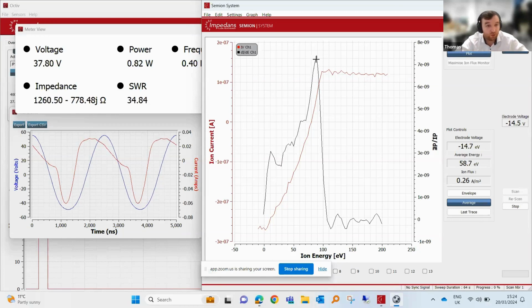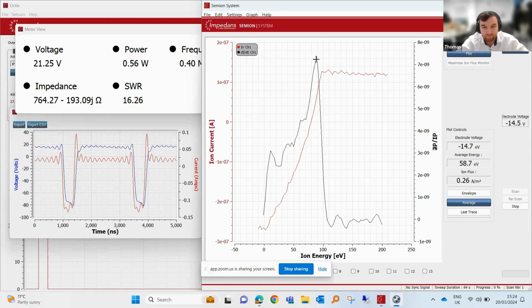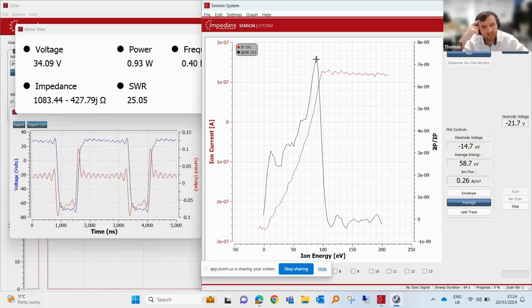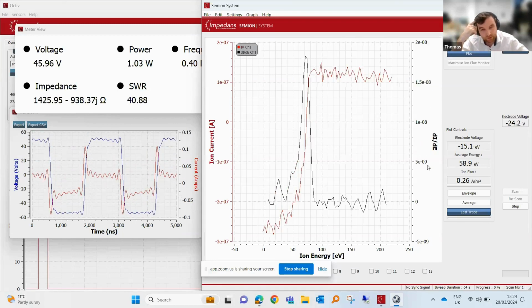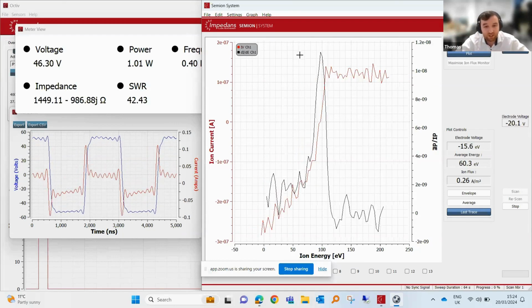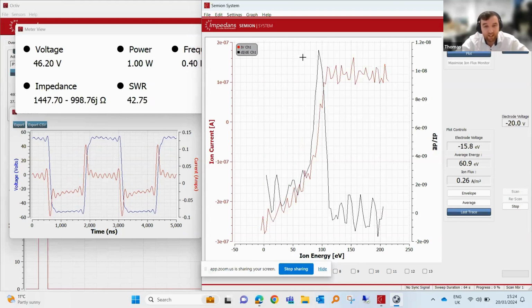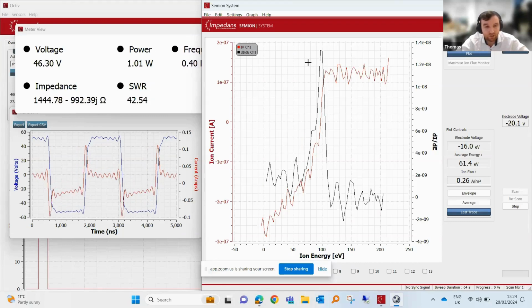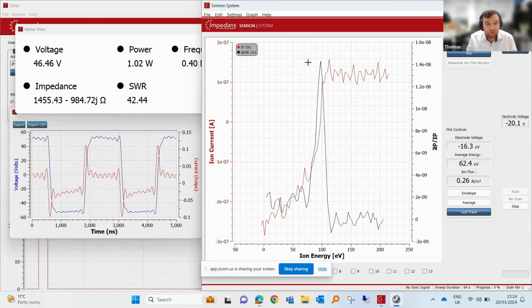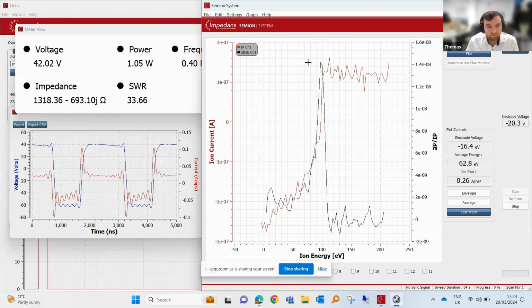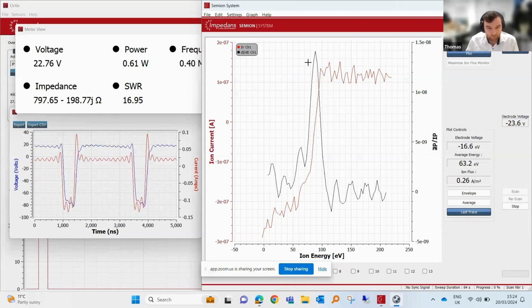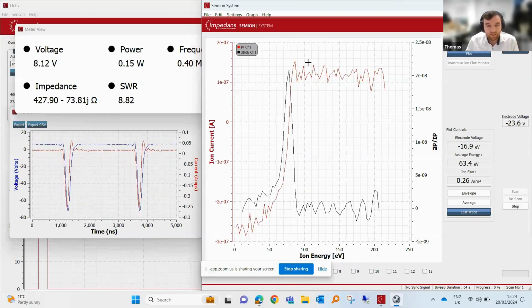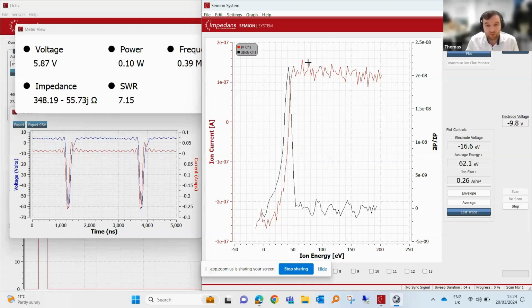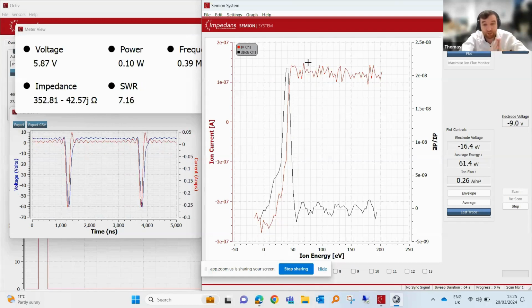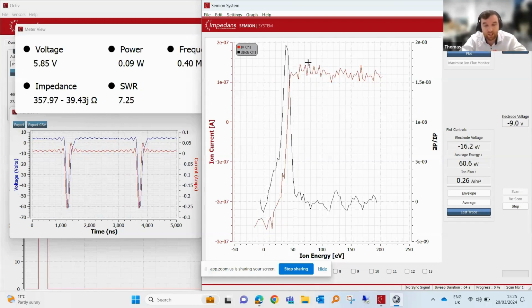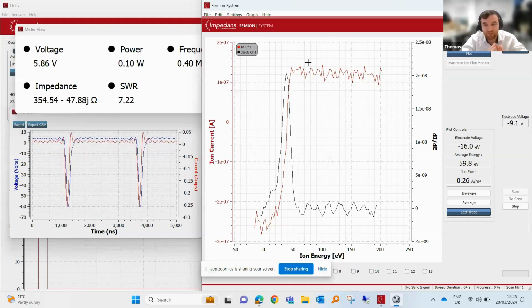Now, can we switch to a square wave, please? Also, can you go on to last trace in the software so we can see what the shape is now? You can see we've already dramatically changed the shape just by going to a square wave. Now, can we change the duty cycle of the square wave? So we're in the pulse DC mode. As we change the duty cycle, you can see the waveform updating, and we're getting a narrower and narrower ion energy distribution function. We've gone from a bimodal distribution to a single, really narrow peak at one energy. This is the sort of control you get from a tailored waveform.